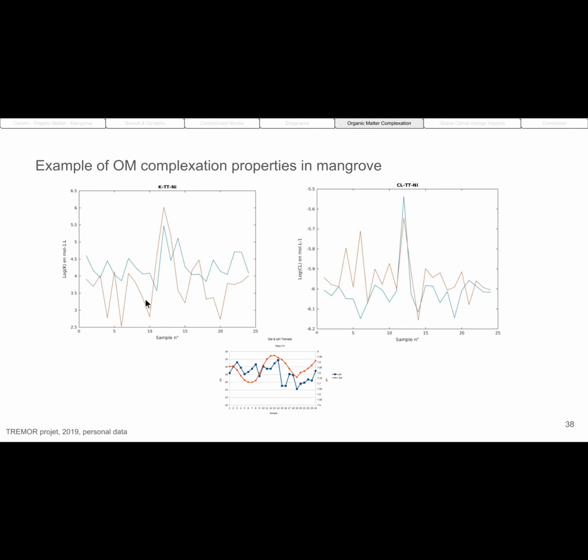For the constant, we observe that during the middle of the experiment, which is high tide during the night, we have a higher complexation strength. It's not linear, it's logarithmic. It means that during this period, we have organic matter that is 100 times more complexant than the usual organic matter. And concerning the number of sites, meaning the number of functions of complexation, there is also an increase here in the middle and a little bit when there is a low tide.